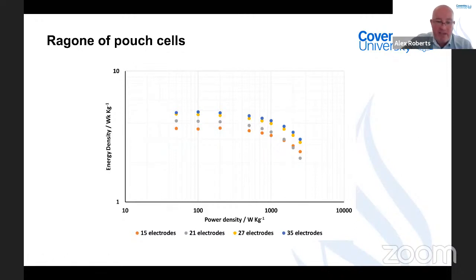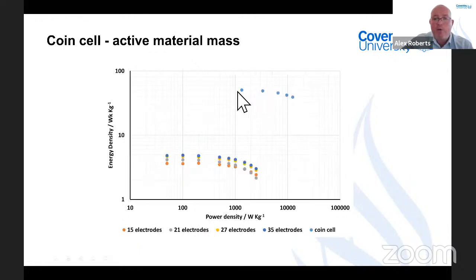If I take the same electrode material and I do the calculation with coin cells, we can see it's now appearing right up here in the top right-hand corner, which is orders of magnitude better in performance than we actually get in the device. So part of this work was looking at how we can scale between these. Given the fact that I actually made the final devices, I can get a realistic and accurate percentage of active material that's going into these devices. So I can apply that mass scaling there.